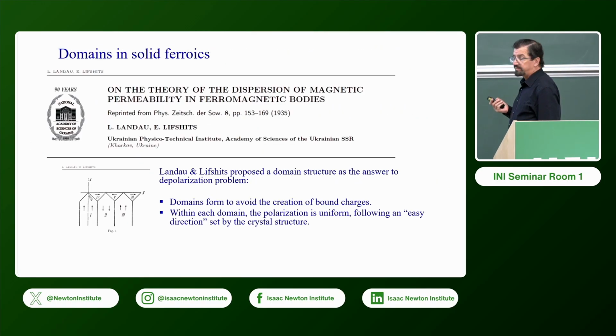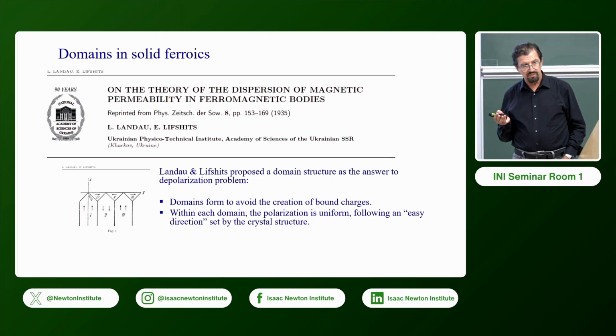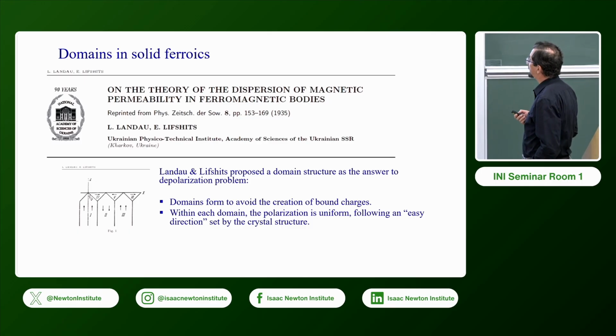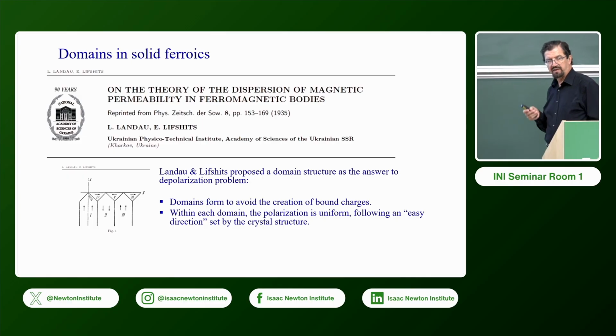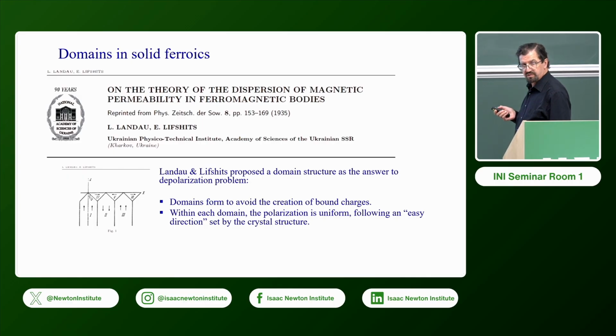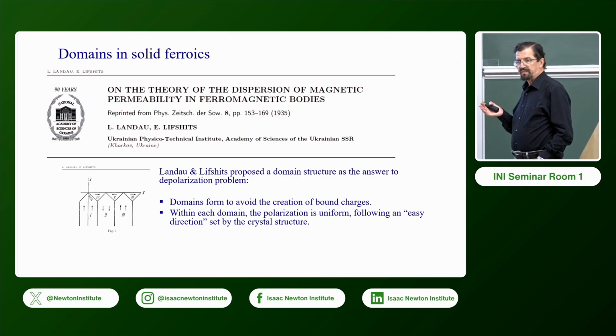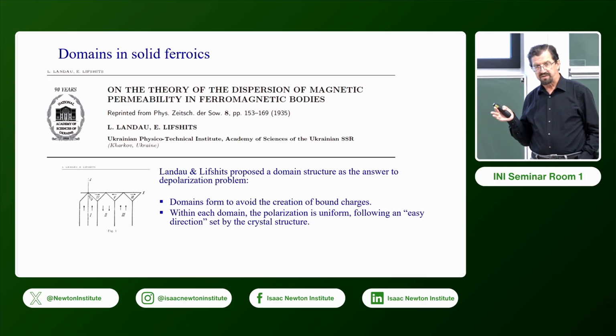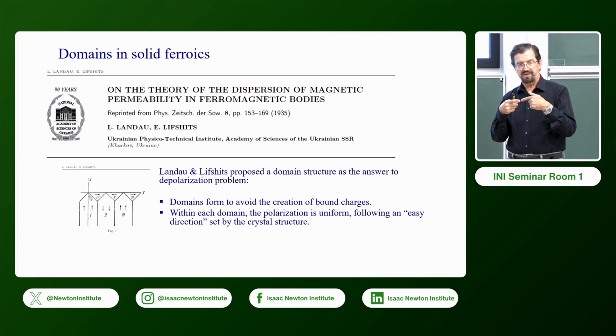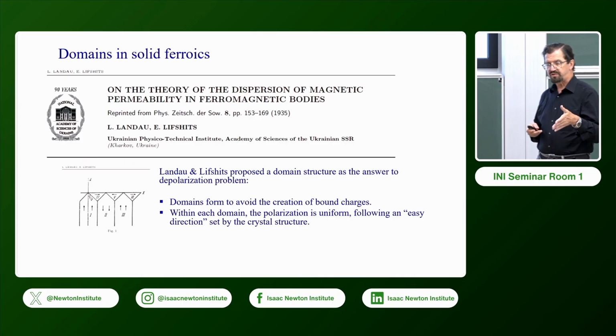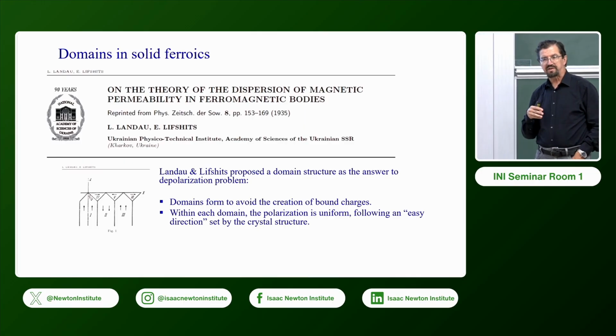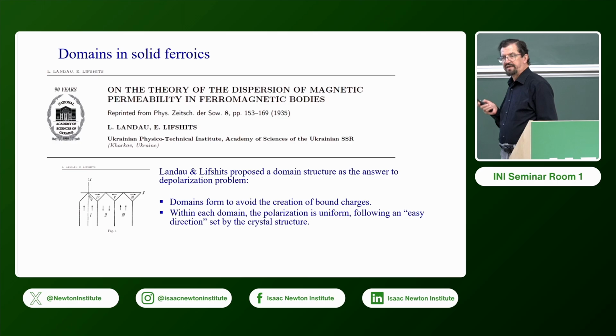So the problem of depolarization field is not new. It has been addressed in the past for the solid ferroelectric materials by Landau and Lifshitz, and then later on by Kittel. And the suggestion was that in order to reduce the depolarization field, the system splits into domains. The domains show anti-parallel arrangement of the polarization. That way, the surface charges alternate between positive and negative, and the total field decreases.